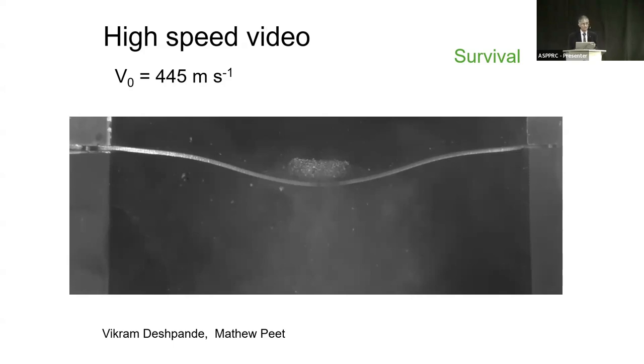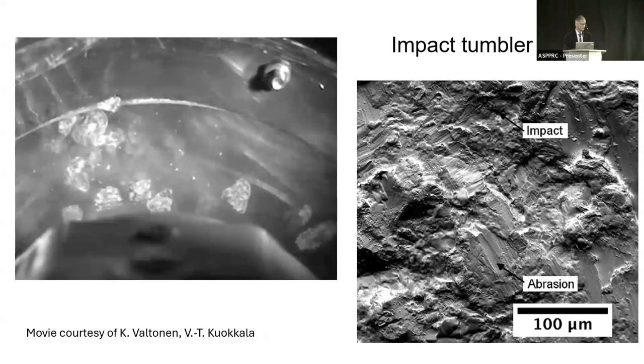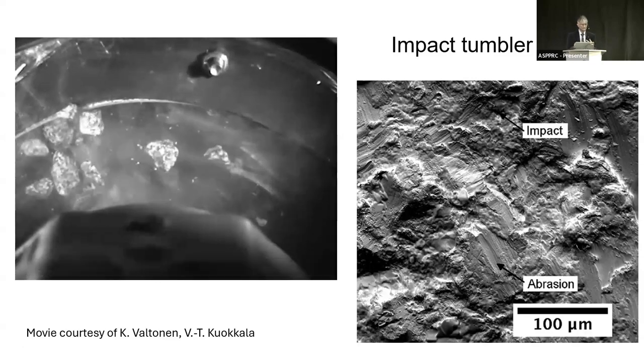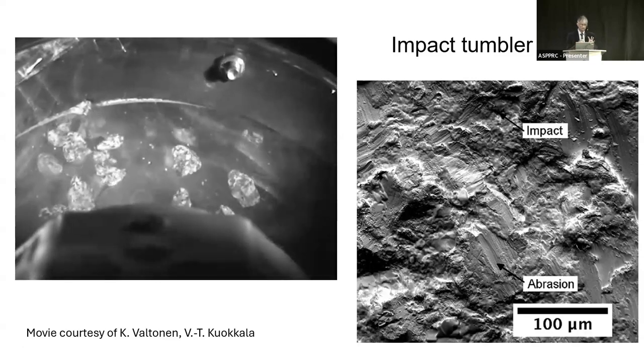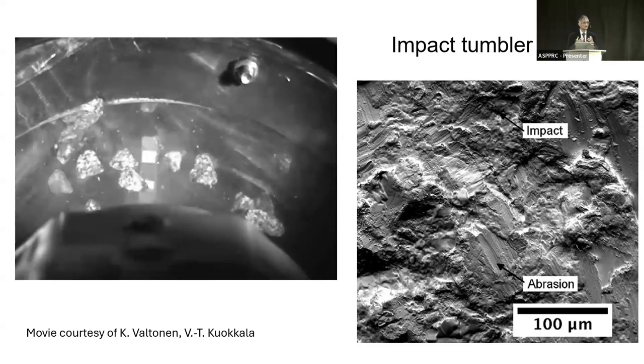So you want to look for a civilian application. And we collaborated with a university in Finland, which has very good facilities for abrasion testing and impact abrasion in particular, where you're scratching the material and at the same time you're impacting it. So you can see here that abrasion damage and impact damage. In the minerals industry, this is really important, okay? And the equipment is you put your material inside this. This is a slowed down movie and it hits granite particles, okay? So you can then work out what is your weight loss and so forth.